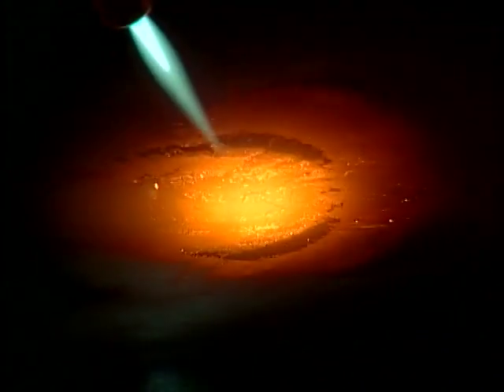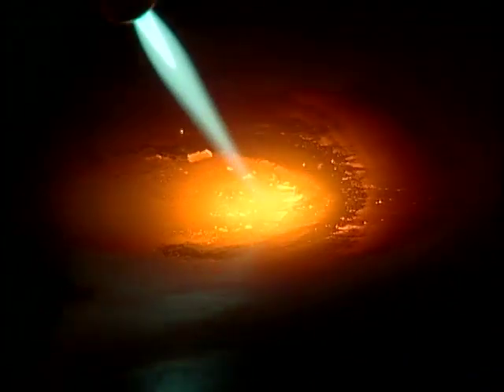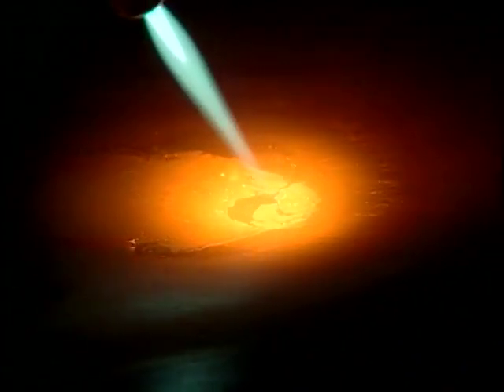A carbonizing flame has excessive acetylene. The weld pool is much wider and has a crusty material floating on the surface. Small sparks are noticeable. A carbonizing flame burns at a lower temperature than a neutral flame. It creates harder, more brittle welds. This is because it adds carbon to the metal.